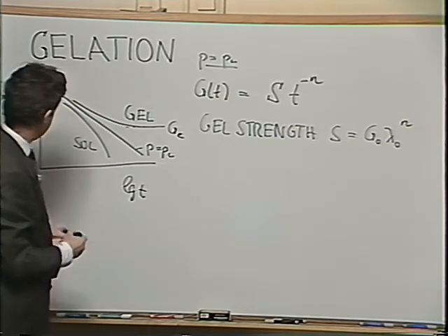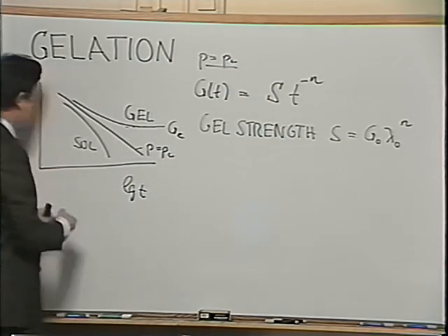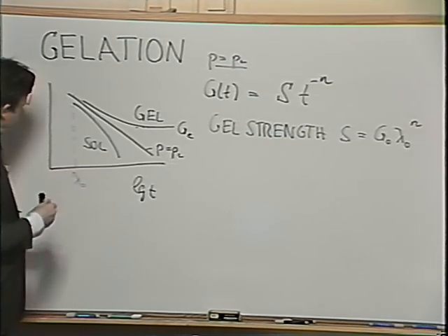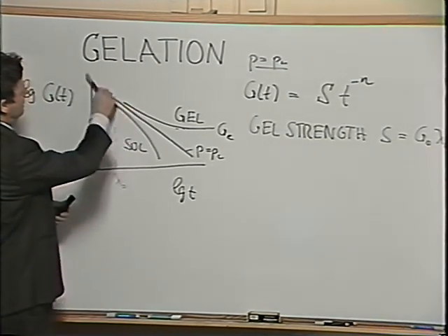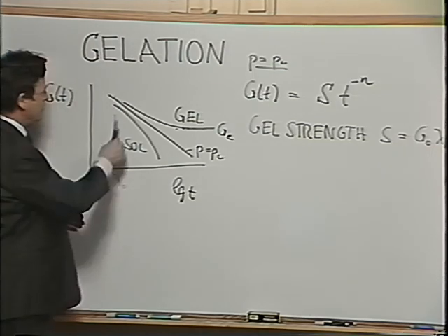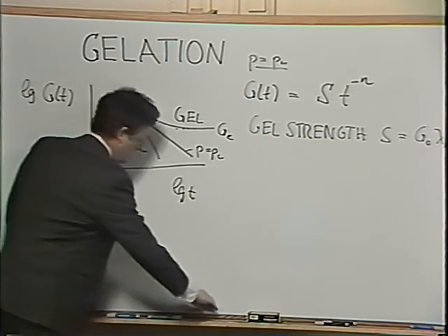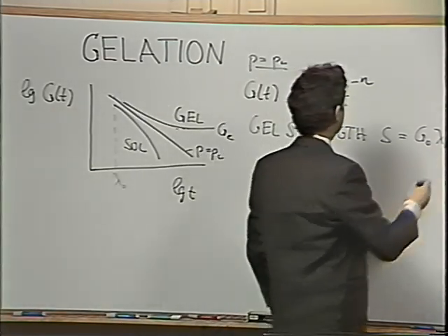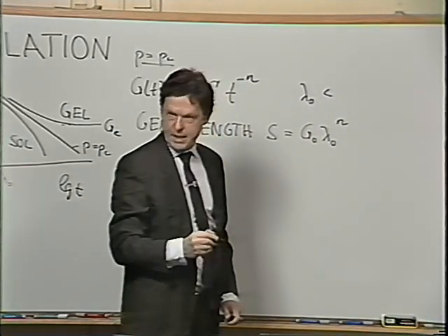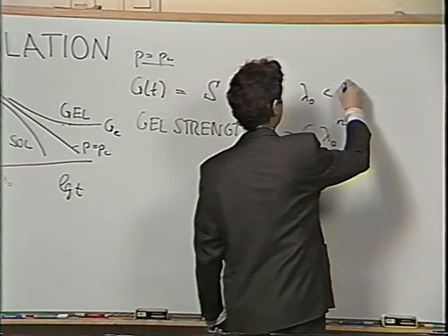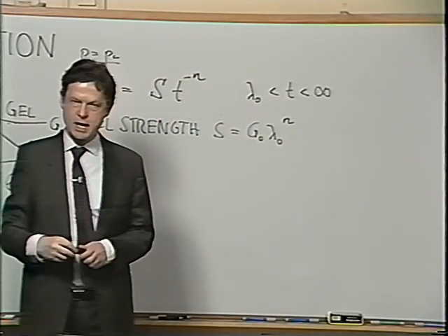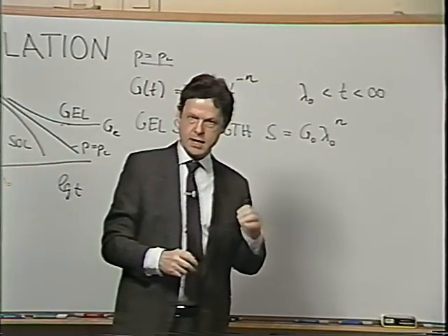plot this modulus. At short times, there will be a transition to the glass, having a very high modulus. We are neglecting this glass transition at the moment, but we could say that this modulus is valid above a certain shortest time for the glass transition and up to an infinitely large time, because the spectrum is really diverging at the gel point.